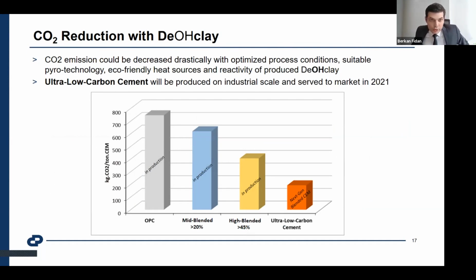When we look at the CO2 reduction and CO2 footprint effect of the dehydroxylated clay, DeOH clay, we produce, this is data from that plant, Abidjan plant, with imported clinker. As you can see, OPC is more than 700 kg, around 700 to 750. With mid-blended cement with calcined clay, the SCM-2 group, as I explained, we could decrease to around 600. And with the high blended group, we could decrease to under 400 kg CO2.